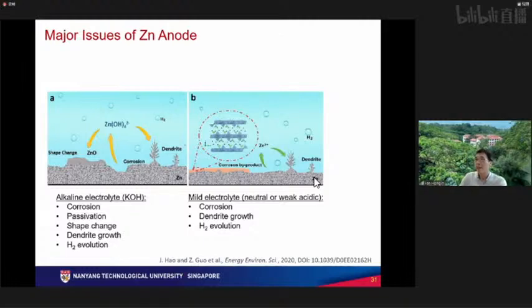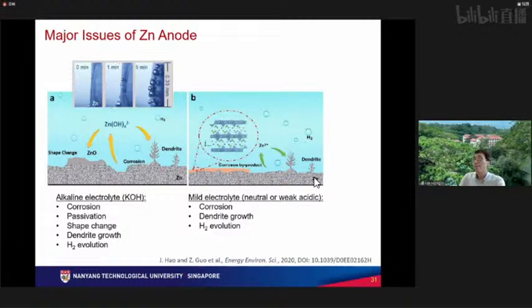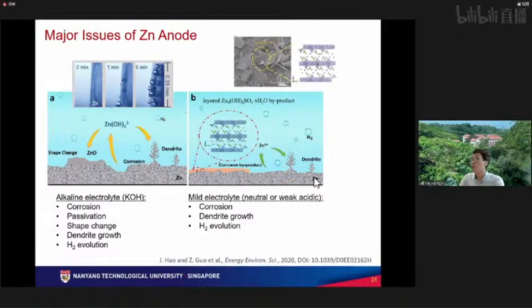This phenomenon is very severe in alkaline electrolytes, but also evident in mild electrolytes, neutral and weakly acidic. All this is observed, either by in situ photos where you can see the bubble generation, or by SEM images that show zinc hydroxide sulfate byproducts, the so-called ZBS byproducts. Sometimes the byproducts can be reversible, sometimes irreversible, depending on how you manipulate the electrolytes. If irreversible, they just cover the surface, on both the cathode and anode sides. Covering the surface consumes charge, consumes alkalines, and makes the surface insulating. So people have to try to eliminate this. There are a lot of challenges there.